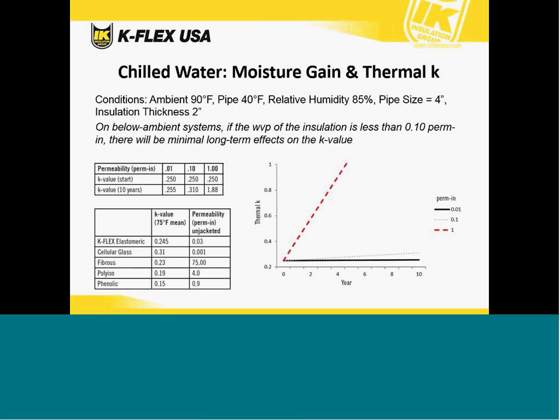And what we show here is that over time, the system with a higher water vapor permeability will eventually get a higher thermal K due to moisture intrusion in that system. The solid black line shows fairly stable thermal K over the 10-year life cycle of this insulation system because the low initial water vapor permeability prevents moisture from penetrating into that system. On the opposite end of the spectrum, the dashed line shows an insulation system with a permeability of 1 on day 1. Over time, moisture will accumulate in that system, which will drive up the thermal K, which will cause you to lose the efficiency of the insulation system. It may cause you to lose the efficiency of your piping system and the water temperature there. It may lead to mold growth and corrosion under that insulation. So keeping the insulation system dry keeps performance stable over the life of that system.